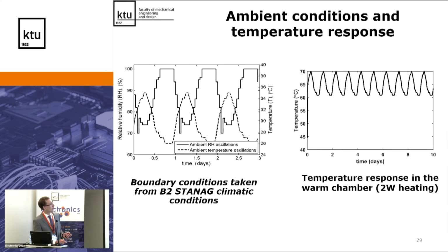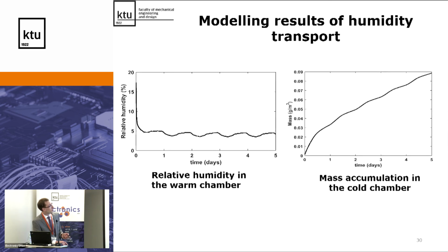And then we applied ambient conditions taken from the B2 STANAG climatic conditions, where it's represented like climates from Australia, from Asia, or whatever, from different regions. And then we applied 2 watts of heating in the warm enclosure. And here's of course the response, how the temperature is responding to the ambient and also to the heating. And we see that the profile of temperature is very similar. And then we can see what is happening with the relative humidity. Of course, relative humidity drops because of the heating.